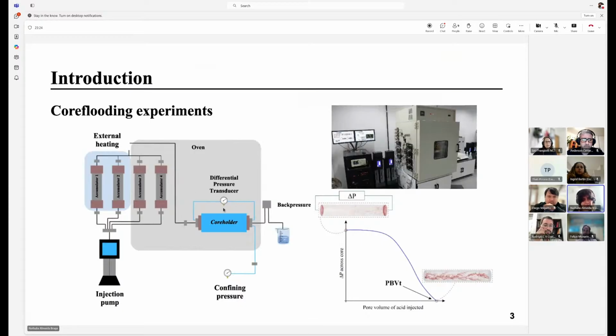There are pressure transducers to monitor the pressure during the whole process. And while the fluid is being injected, we see that the difference in pressure between the inlet and the outlet of the sample begins to fall as the acid moves through the sample and starts opening these wormholes. The resistance to the flow starts to decrease until it reaches a minimum point that we call breakthrough. It means that the wormhole went from the inlet to the outlet of the sample. And this scale is what is being simulated with my computational model. It basically represents a core flooding experiment.